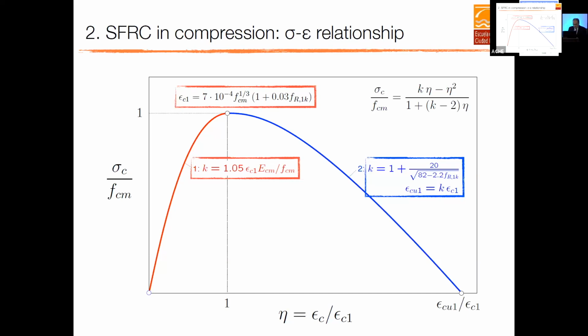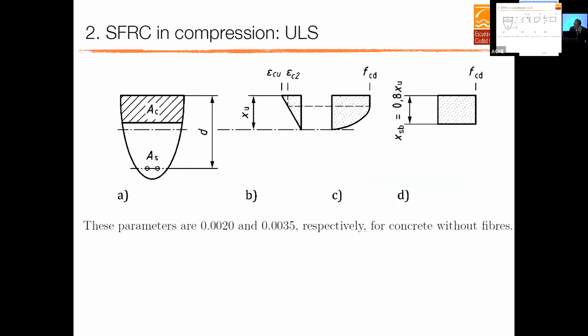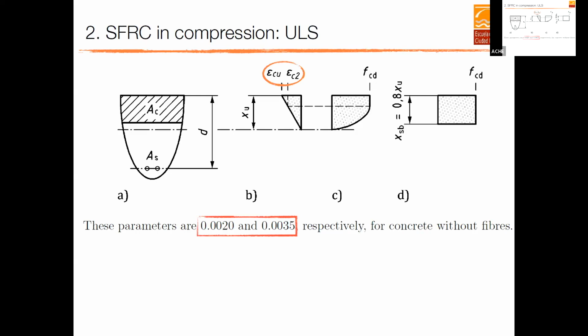We also made a contribution for the ultimate limit state. In this case, you know that we use the parabola-rectangle curve, which is mostly defined by these two parameters plus the strength parameter, of course: the ultimate strain and also the strain for the peak. These parameters for plain concrete are 0.2% and 0.35%.